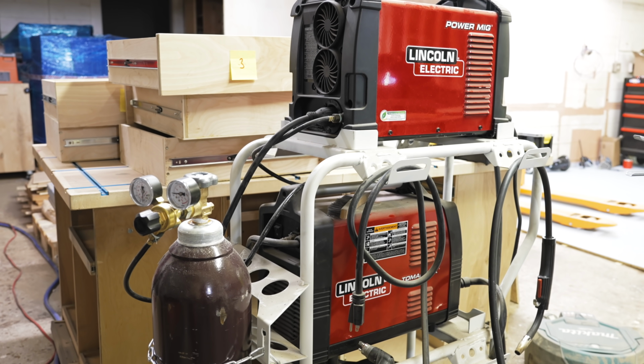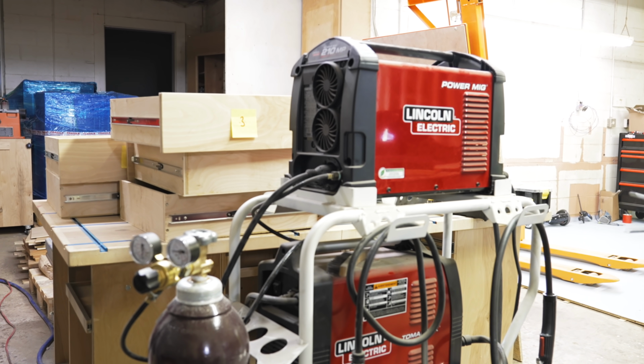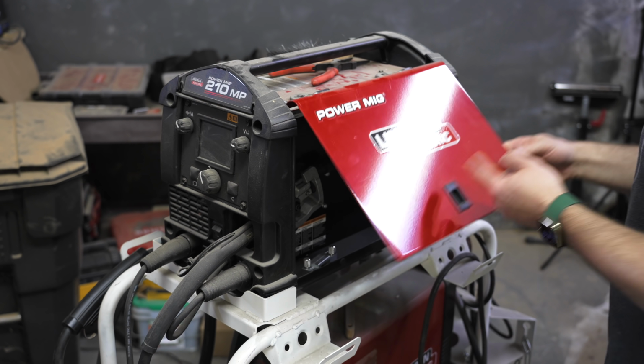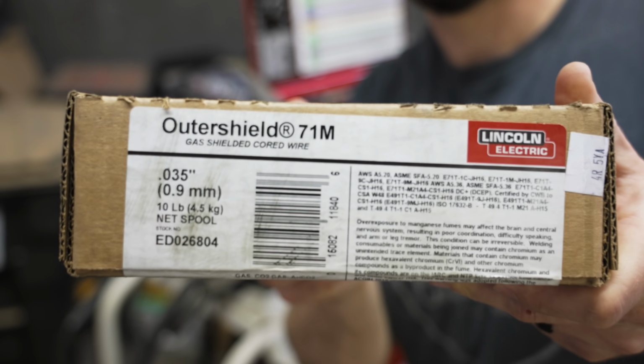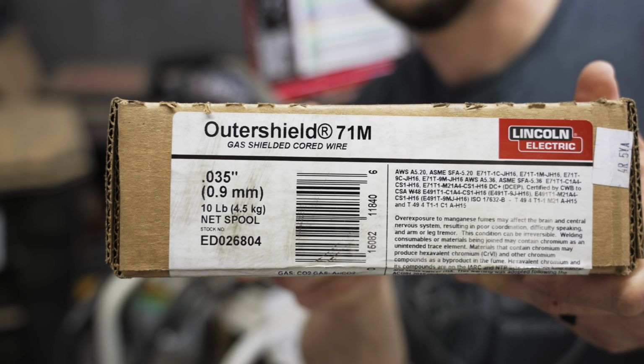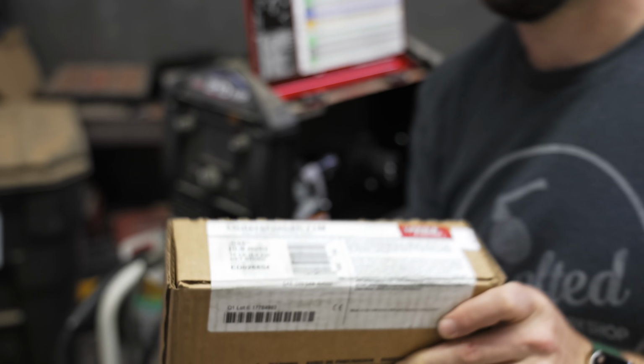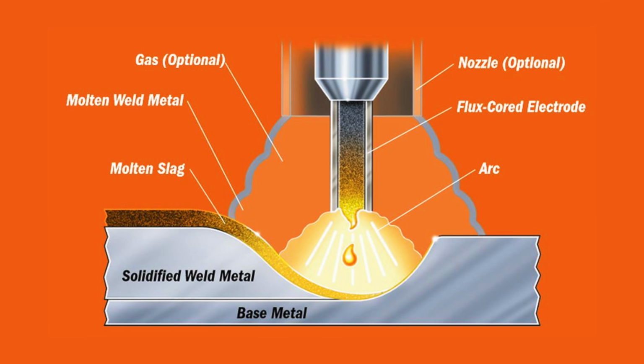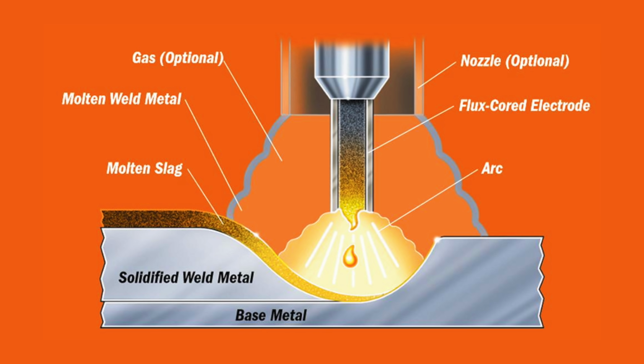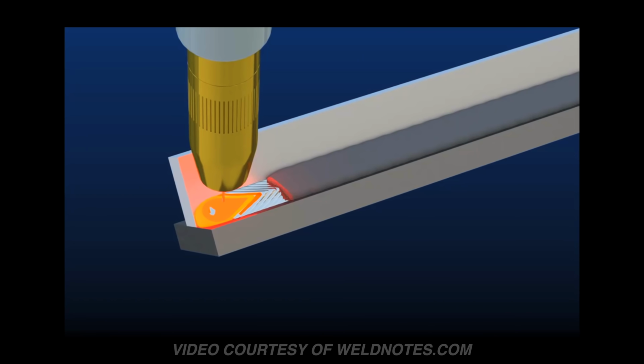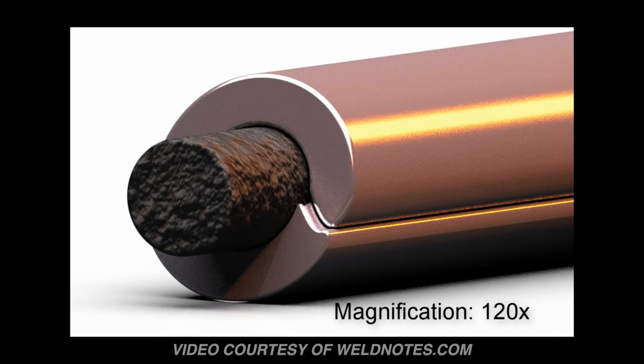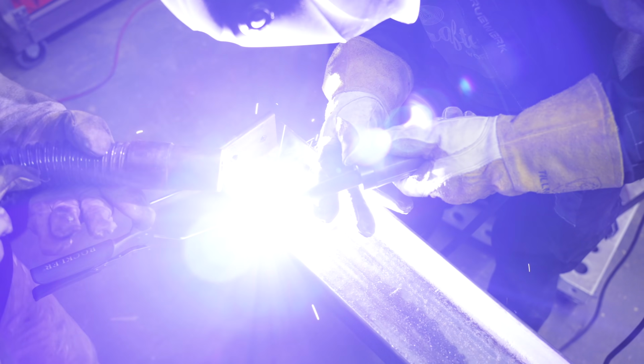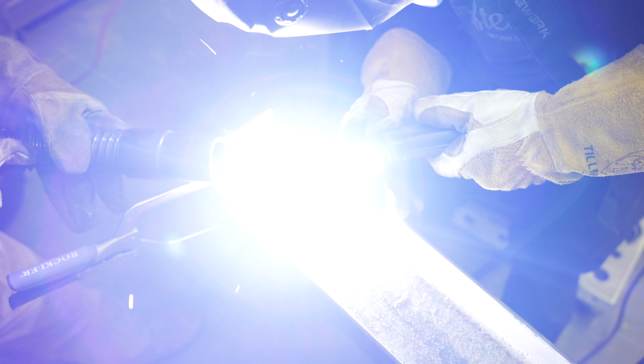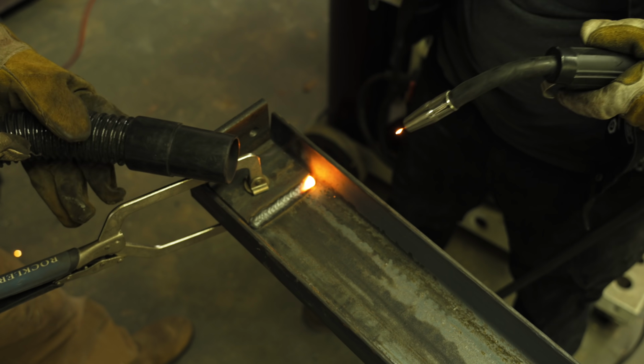While the guys worked on getting the steel prepped, I worked on getting my trusty Lincoln Electric PowerMig 210MP welder set up. For the wire on this job, I went with Lincoln's Outer Shield 71M, which is a dual shield flux core wire, meaning the puddle is protected by both shielding gas and the slag formed during the welding process. And dual shield flux core is ideal for this kind of structural steel work, as you typically get really good penetration and can lay in a lot of filler material very quickly.